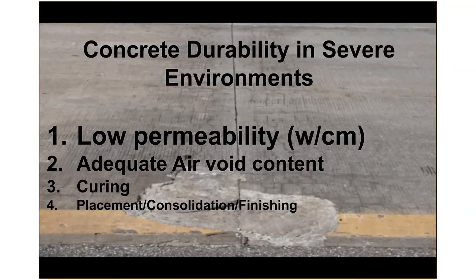So lastly, placement, consolidation, and finishing. Finishing has a great deal to do with surface durability, working water into the surface, working up a laitance or high water cement ratio surface would degrade the surface longevity. Placement and consolidation, getting a concrete consolidated, and so there's no honeycombing and all that. And we're going to look at what's very interesting about this concrete with regards to consolidation here in just a minute. And again, the placement methods nowadays, we're getting the concrete to move where we want to by using vibratory